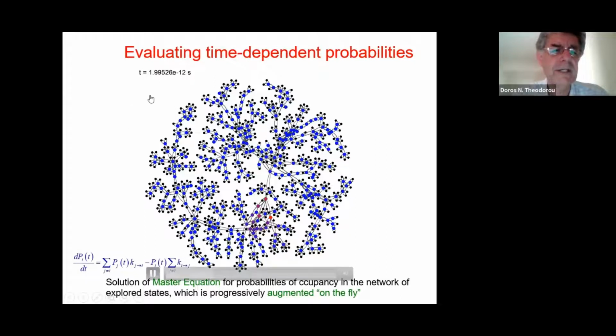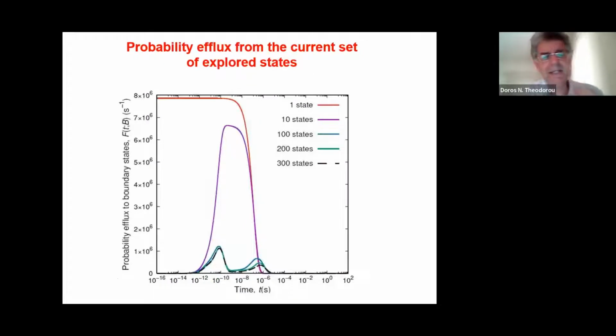Here we see the clock running in this simulation, and you see the colors changing because whereas originally all the probability was placed in one minimum, now it is spreading to other minima through these transitions across saddle points. So in the end, one can observe the system for a rather long time. In this case, it was a millisecond at which the simulation stopped. So one has the probabilities of occupancy of these minima, and one knows what the minima are. So one has also the properties of these minima. So one can try to calculate the properties of the relaxing glass.